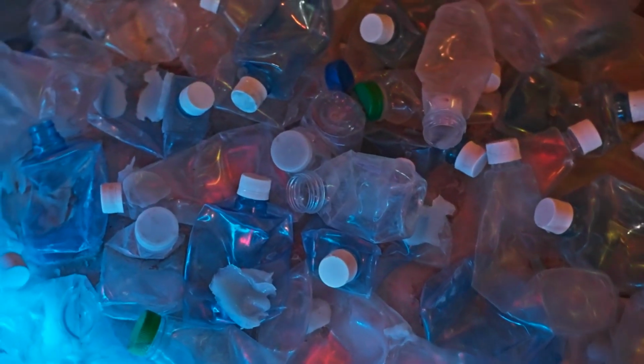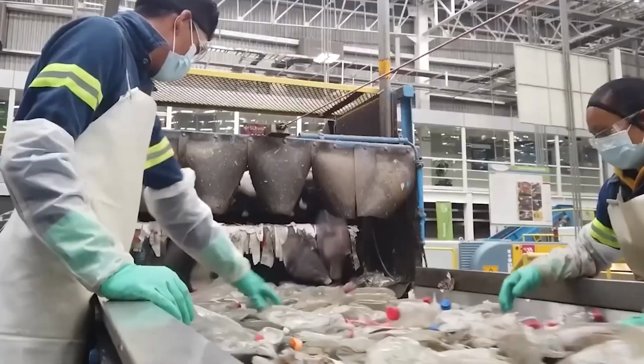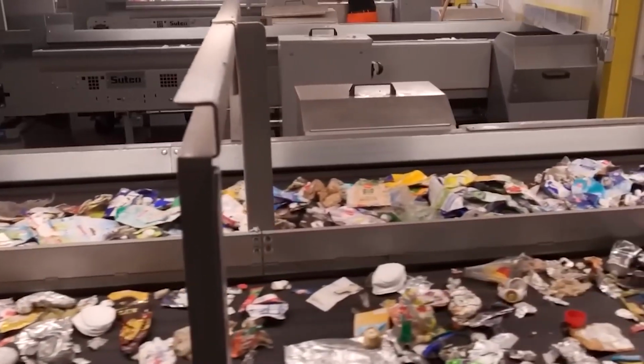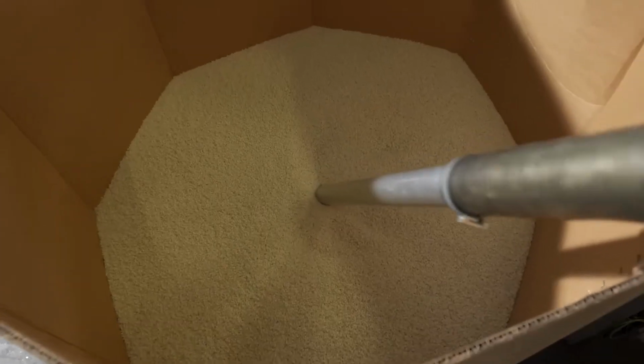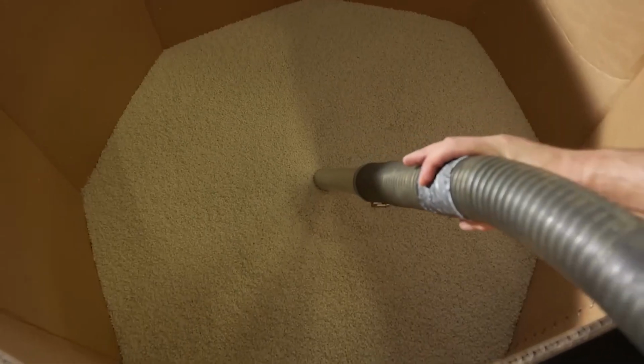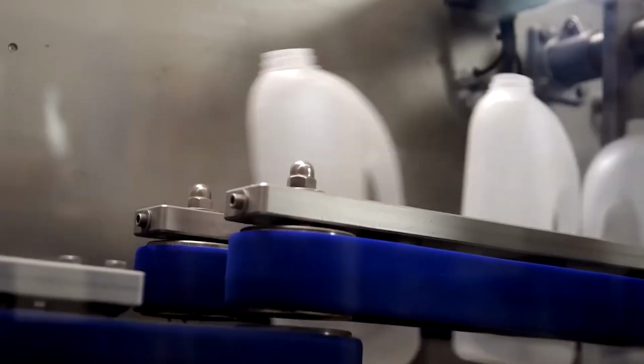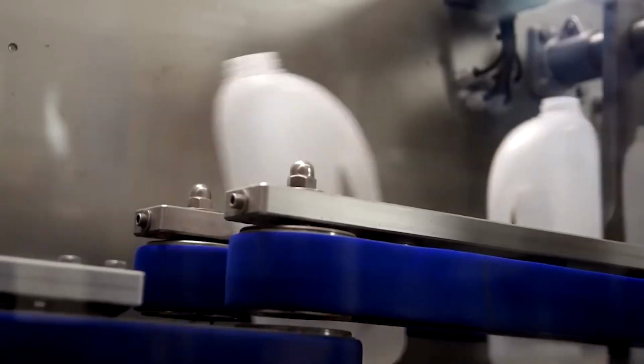Even after cleaning, grinding, and drying, one challenge remains: microscopic impurities within the same plastic type. Small variations in color or transparency invisible to the naked eye affect final product quality. AI-powered hyperspectral cameras scan each tiny piece, analyzing transparency, reflectivity, and surface color. Upon detecting contaminants, high-speed airstreams immediately remove faulty pieces from the line. With 95% plus accuracy processing 1,000 pieces per second, these systems ensure only the purest material proceeds to final conversion.